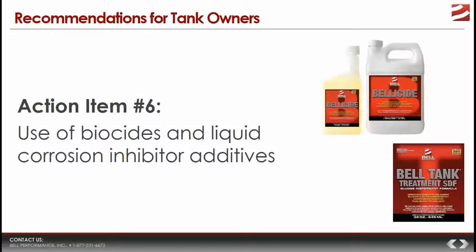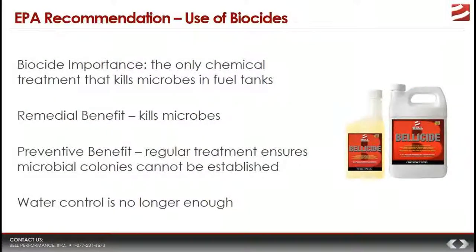So what is it about these that made the EPA specifically call these 2 kinds of treatments out? Why did they do that? Well, because the EPA knows that biocides and corrosion inhibitors directly address the problems that tank corrosion is associated with. So let's talk about biocides. Given the link between storage tank corrosion and microbial activity, it stands to reason that the EPA would recommend that tank owners incorporate something into their housekeeping that most directly targets microbial growth. And biocides, as a class, are the only chemical treatment that kill active microbes. So you can use them in both a remedial manner and in a preventative manner. If you have a tank and it has microbial-induced corrosion signs in it, then very likely it also has microbes in it. It has an existing microbial presence.